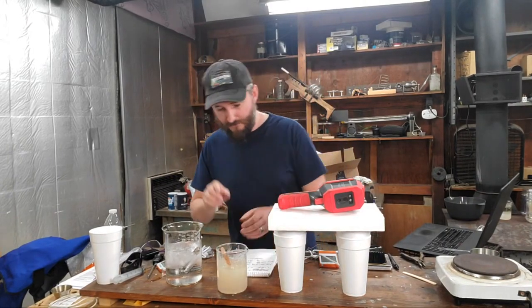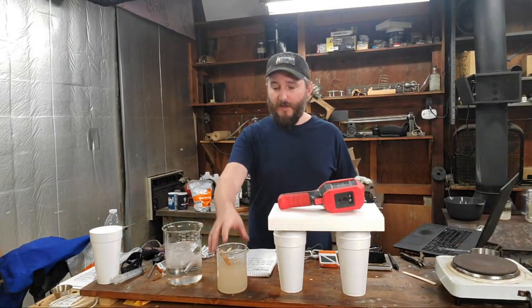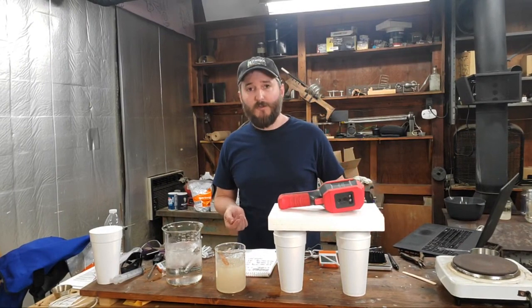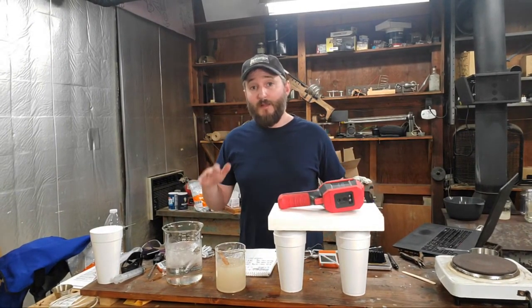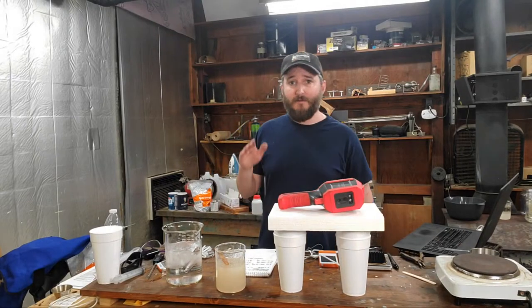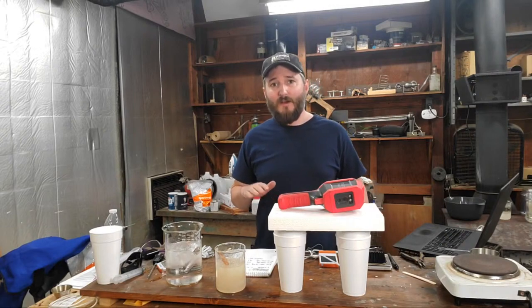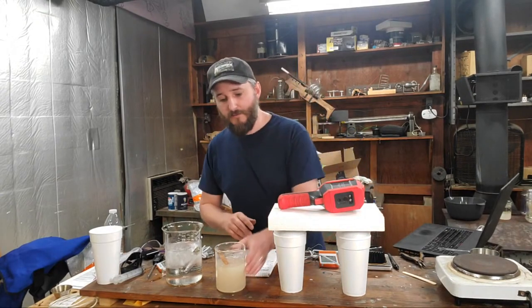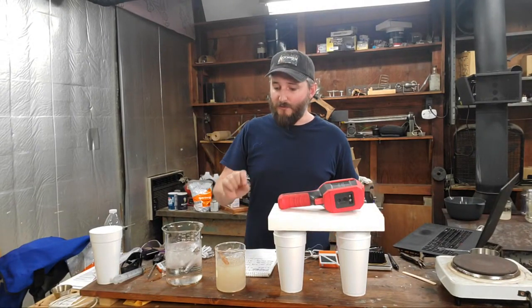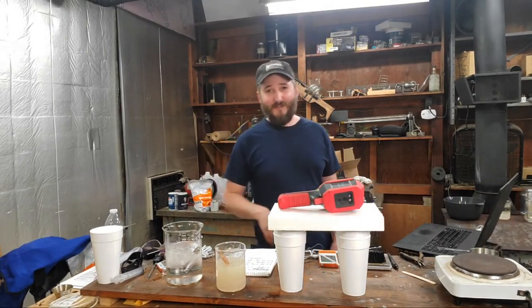But primarily this is sodium sulfate, sodium chloride, table salt, and then xanthan gum. And that mixture in a particular ratio with water makes this phase change material that starts its phase transition right around room temp, and then it continues that phase transition all the way down until sub water freezing temperature. I think it has actually a pretty hard phase change at around -16 degrees Celsius. I think it undergoes another phase change where it's the final one and you end up with a completely solid material. But everywhere from room temp all the way down to -16, in that whole range there, it's partially liquid and partially solid, getting progressively more and more solid and releasing more and more heat. It's cool stuff.